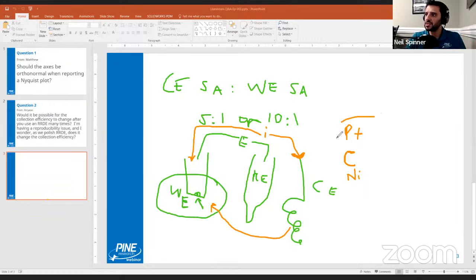But that being said, platinum is probably just overall the most popular. Platinum is a noble metal. Of course it's expensive, but it works very, very nicely. It's very conductive, and it performs electrochemical reactions very, very easily. It's a very ideal counter electrode. But graphite, carbon, in various forms, a rod or plate or something like that. A graphite rod is an easy counter electrode as well. That can be used. It's also a lot less expensive. But again, it just depends on the situation that is being tested in, if it's stable or it's going to dissolve or whatever. So these are the most common that are used, and mostly, like I said, the surface area is really the thing that matters the most.